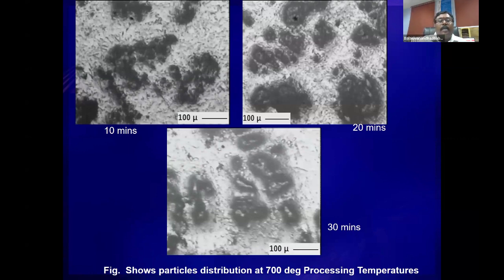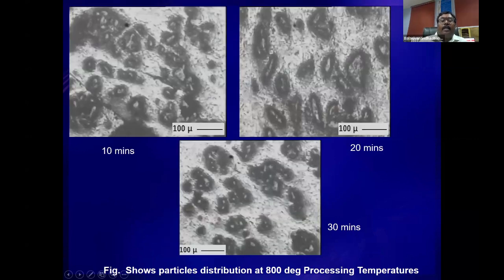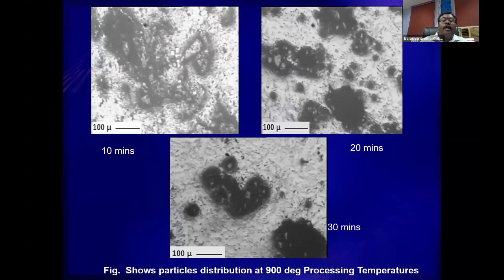Finally, at 700 degrees centigrade, we end up with a larger amount of agglomerated structure. So for the silicon carbide particles, I could see an agglomerated form. And when I increased the temperature to 800 degrees, the agglomeration was broken and you can see a good homogeneous distribution of the particles. And again, when it is increased to 900 degrees centigrade, further agglomeration starts. So that means by only increasing the temperature, one cannot achieve good homogeneity, because something else is happening there.